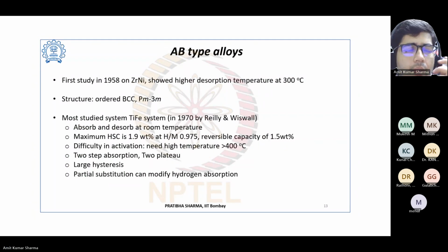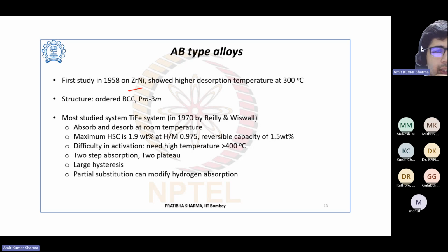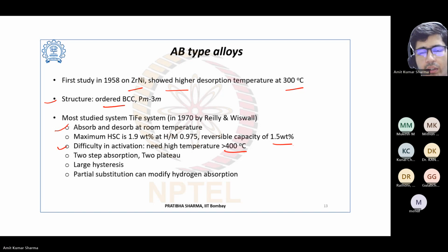Then AB type alloys. These were first studied in 1958 on zirconium and nickel, and showed higher desorption temperature at 300 degrees centigrade. Structure: ordered BCC. The most studied system is the TiFe system, in 1970 by Reilly and Wiswall. These alloys have absorption and desorption at room temperature. Maximum HSC is 1.9 weight%. At HM 0.975, reversible capacity of 1.5 weight%. But it's also difficult to activate these alloys. You need high temperature, greater than 400 degrees centigrade.